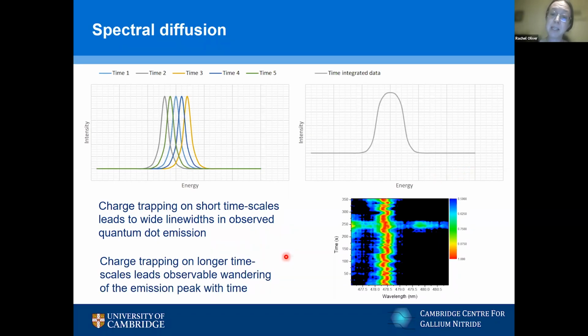Sometimes the charge trapping phenomenon is happening on a much longer time scale, and we can actually measure it happening, watch the line from the quantum dot wandering about in wavelength space. So this graph here has time up the y-axis, and the wavelength of emission on the x-axis, and the intensity of the emission is plotted as the color, with the bright emission being the red part. And we can see that this red band changes by a few tenths of a nanometer every few seconds, basically hopping from one state to another as a particular adjacent charge or adjacent state charges and discharges.